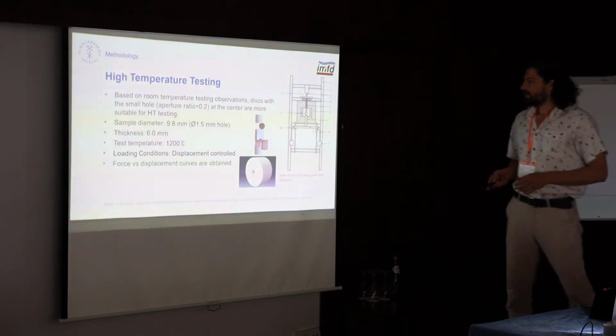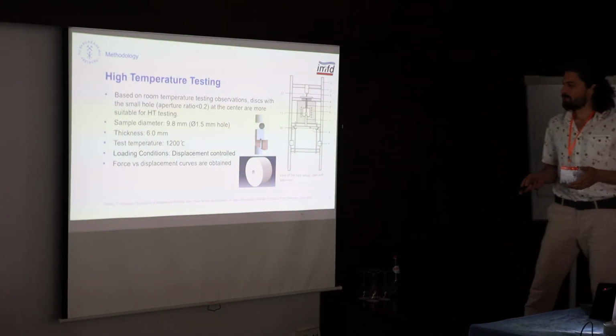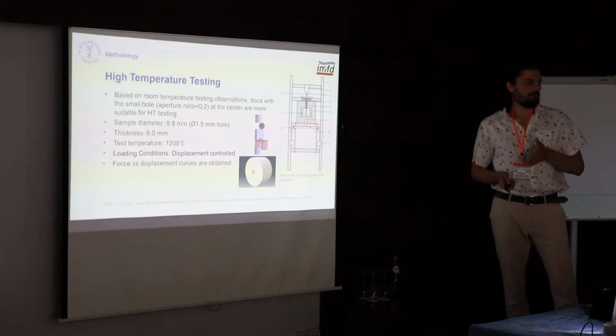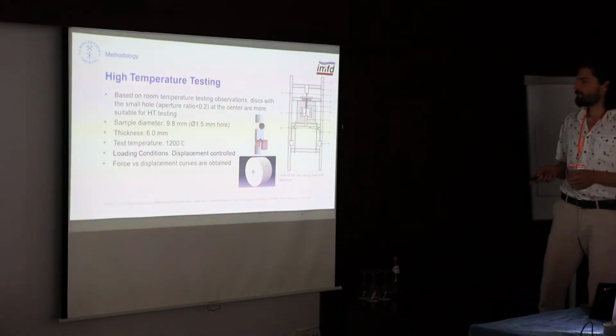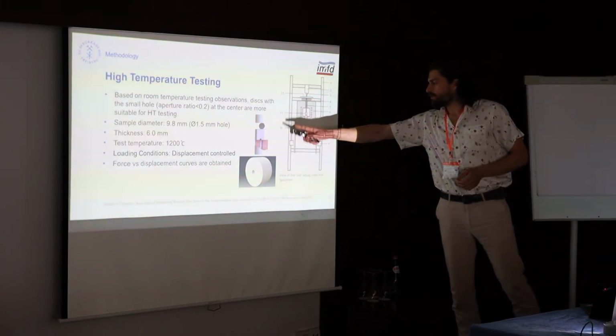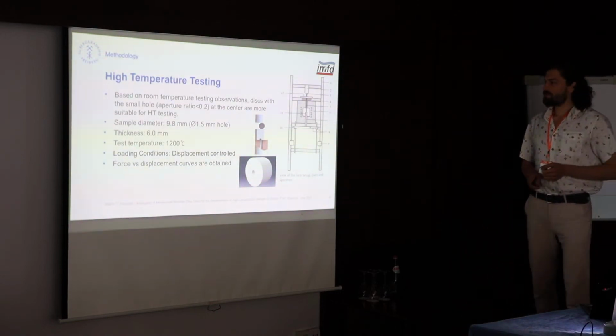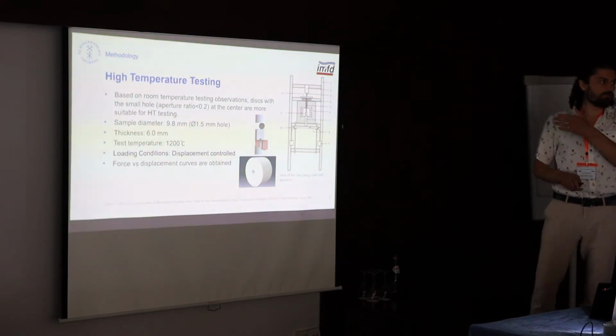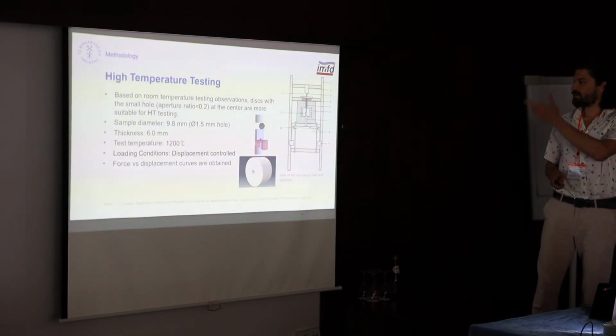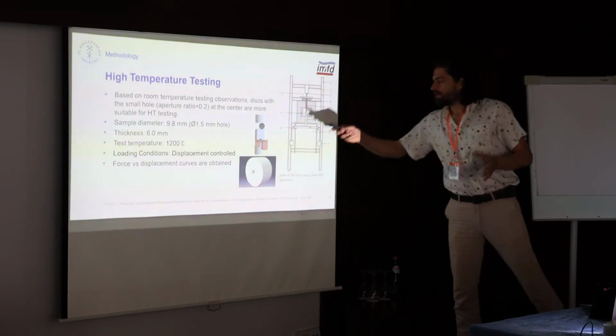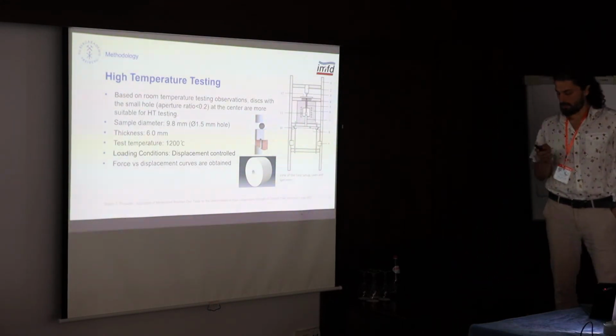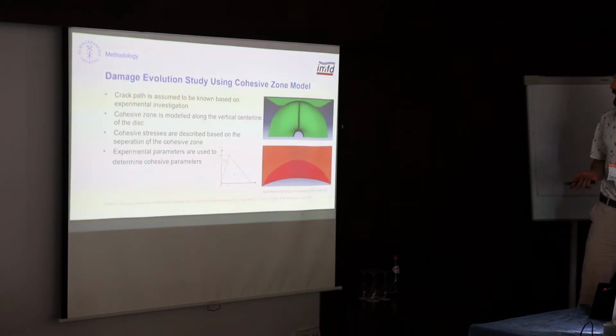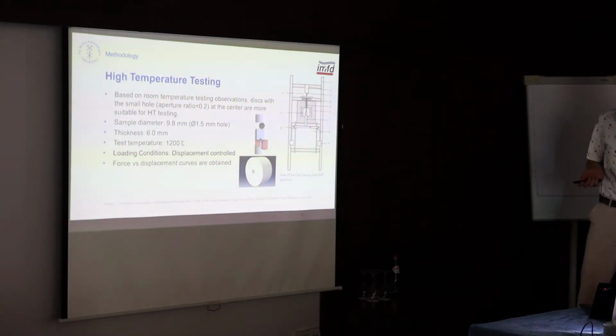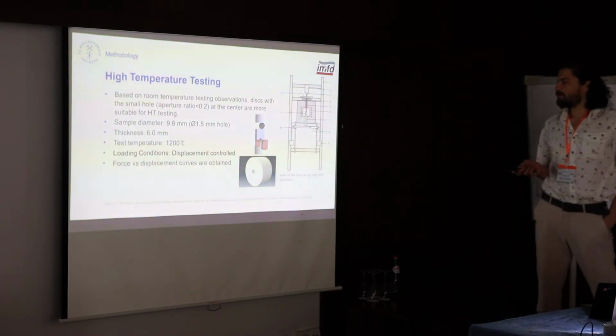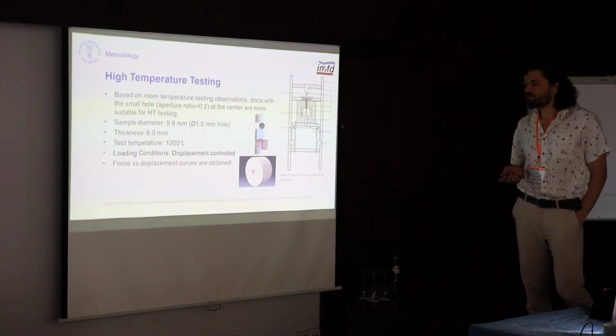And also the second thing, and the most important one, was the predictability of the crack path, which will bring me to my applied modeling. And by the way, also in order to prevent the oxidation of the carbon inside the material, argon gas flows here to make a protective, neutral environment. And by the way, I also made these specimens a little bit smaller to decrease my loads. And the test temperature was 1200.